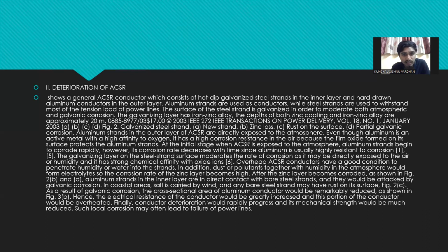At the initial stage when ACSR is exposed to the atmosphere, aluminum strands begin to corrode rapidly. However, its corrosion rate decreases with time since aluminum is usually highly resistant to corrosion. The galvanizing layer on the steel strand surface moderates the rate of corrosion as it may be directly exposed to the air or humidity and it has strong chemical affinity with oxide ions.